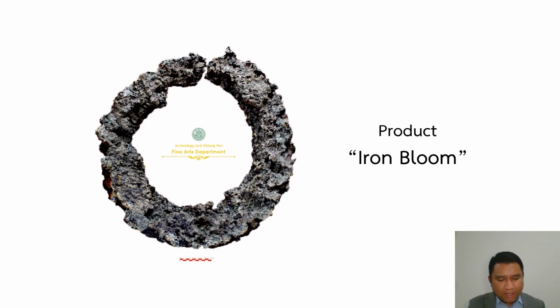Finally, the productivity from this iron smelting is 47 kilograms of iron bloom in a special ring shape, which is shown on this slide. If combined with other pieces of iron, the total productivity obtained from this iron smelting is up to 50 kilograms. In this archaeological experiment, 100 kilograms of iron ore and 380 kilograms of charcoal were used.